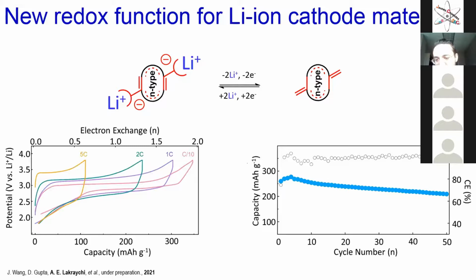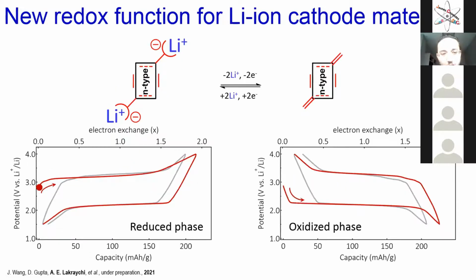So what you need to do here is just to work on the electrolyte and on the electrolyte formulation in order to make it stable during cycling. Here is another molecule that belongs to the same redox class, and as you can see, we have good capacity. So the good news with this redox function is the high capacity with the lithium containing and sometimes the high voltage characteristics.